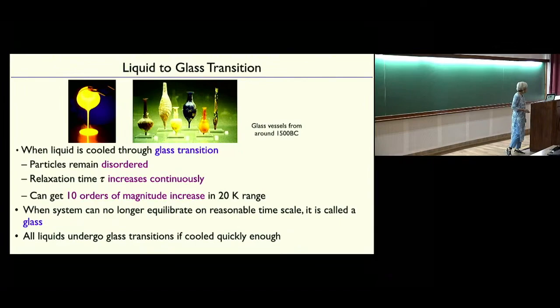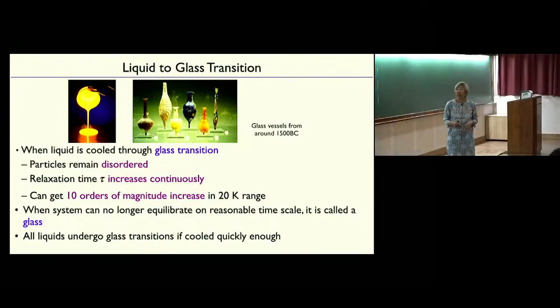Okay, so the liquid to glass transition occurs when you cool a liquid. When you do that, the particles remain in disordered configurations while the relaxation time increases not only continuously, but extremely rapidly, often 10 orders of magnitude in just tens of degrees. And so when people run out of time to measure the relaxation time, so the system can't reach equilibrium, it's by definition far from equilibrium. At that point, the system is called a glass.